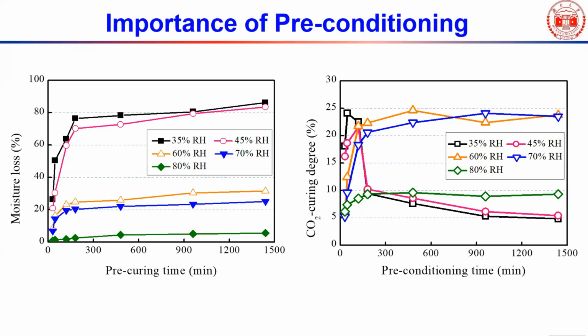And so then you can see, if we look at the green line, which was conditioned at 80% relative humidity, the carbonation degree reached only about 10%. But for 60, 70% preconditioning, you can see initially the carbonation degree increases quickly and then reaches a plateau. But for 35 or 45% relative humidity preconditioning, in a very short time period, it can reach a high carbonation degree. But on the other hand, as the preconditioning time increases, the carbonation degree drops very quickly, right?